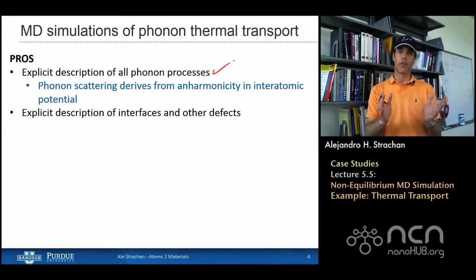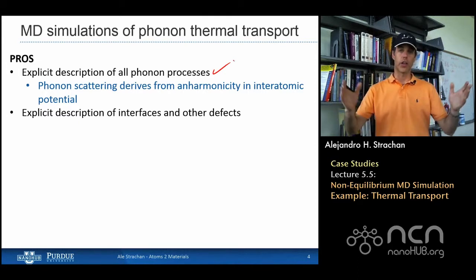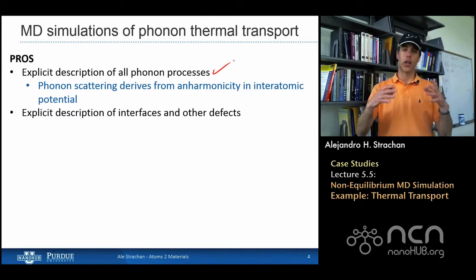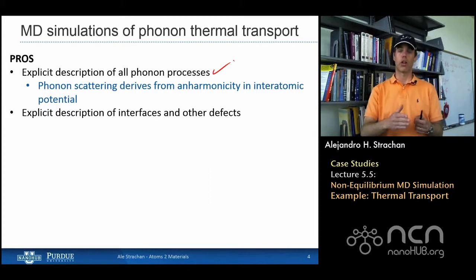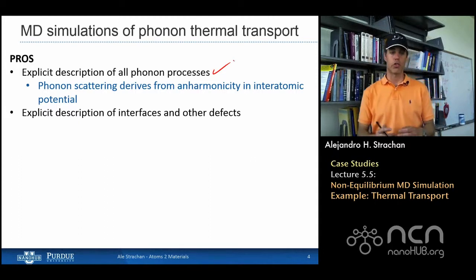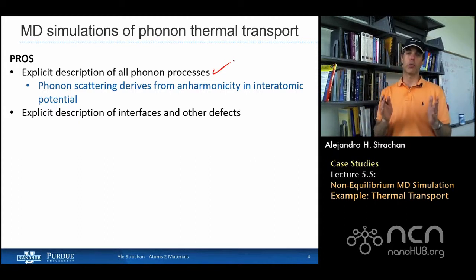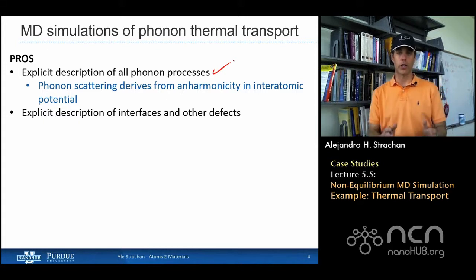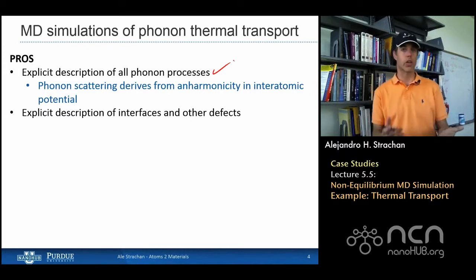Now, if you remember what we've learned during the lectures, within the harmonic approximation, if I take my system of atoms and I expand the potential energy up to the second order, and I do a diagonalization of the Hessian matrix, my system can be described as a set of non-interacting independent harmonic oscillators. If that's the case within the harmonic approximation, the thermal conductivity of the material is infinitely large. Okay, there's no scattering mechanism to slow down the flux of heat.